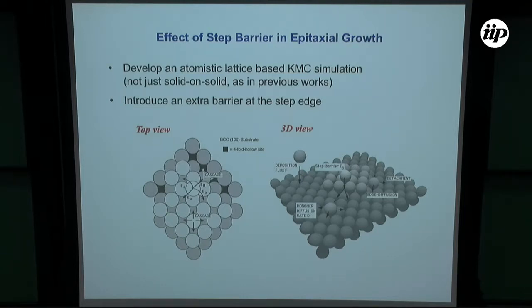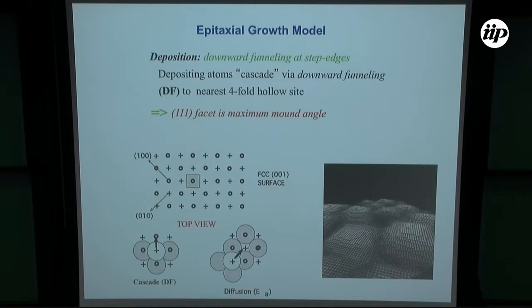That's why it's called a solid on solid. Whereas in reality, if you want to include the step barrier, what you have to do is remember that when atoms are deposited, they form a surface like this, where there is a 4-fold hollow where an atom can sit. And atoms cannot really sit on top of another atom. They move, they diffuse. Once the atoms diffuse, they diffuse into a 4-fold hollow. So the simulation had to be done by looking at a realistic surface.